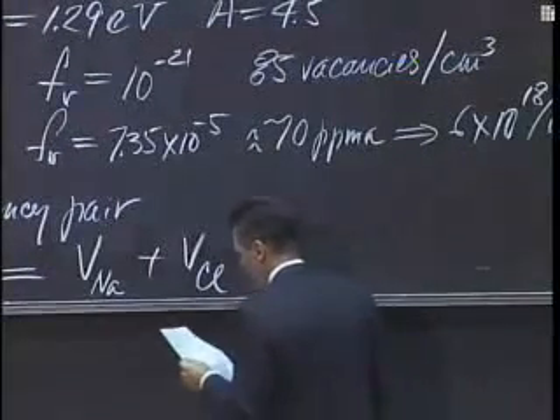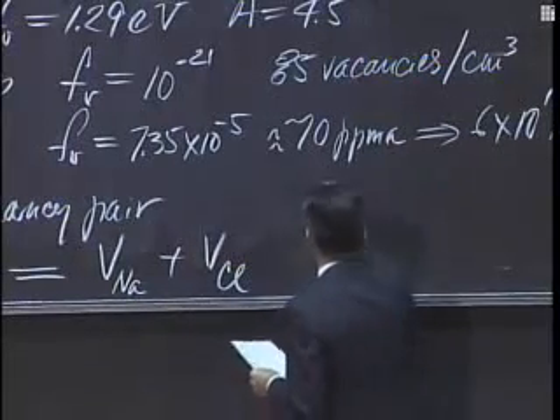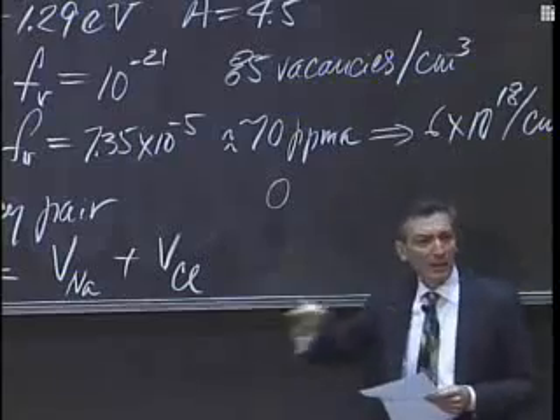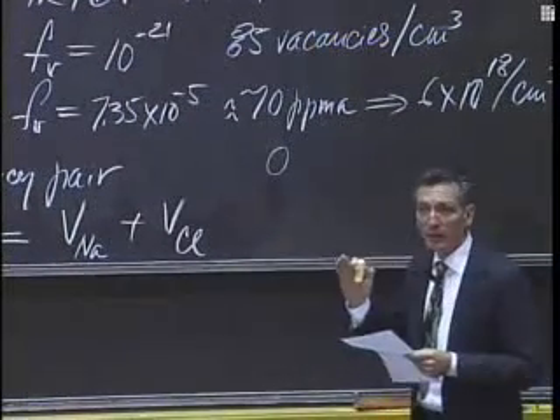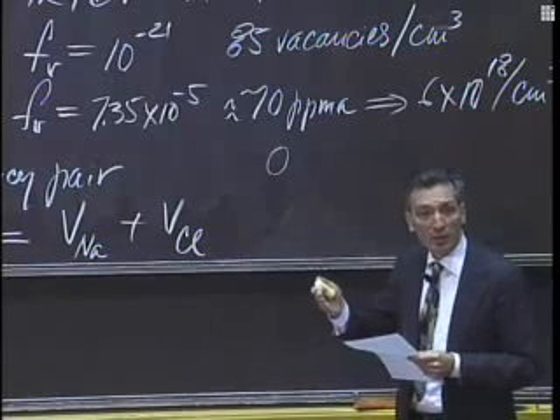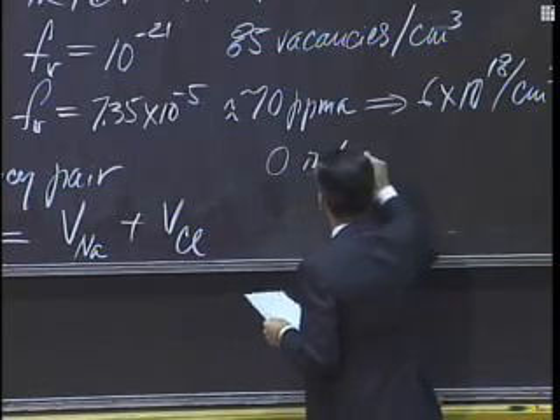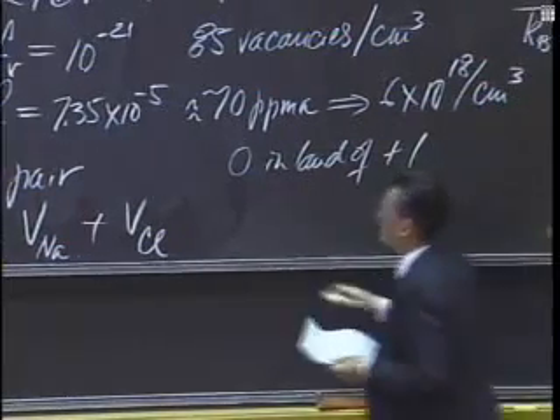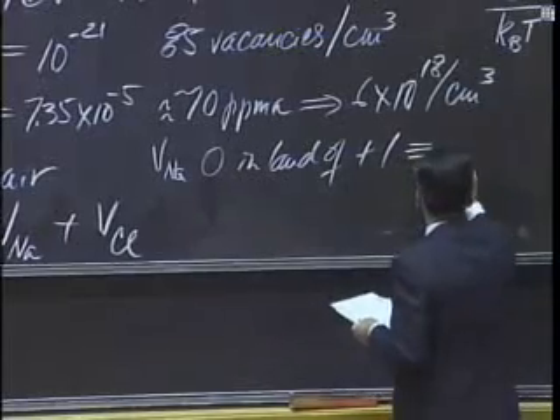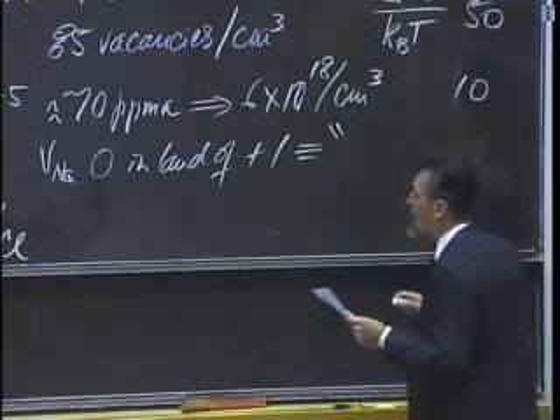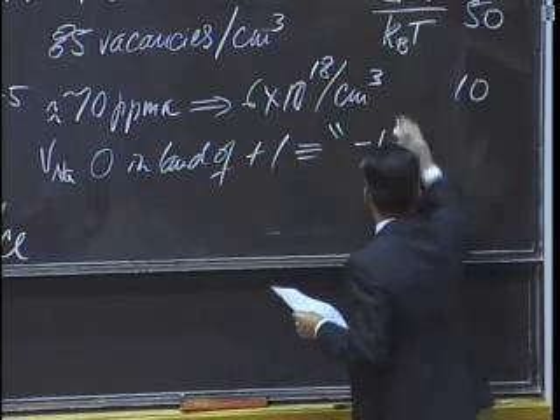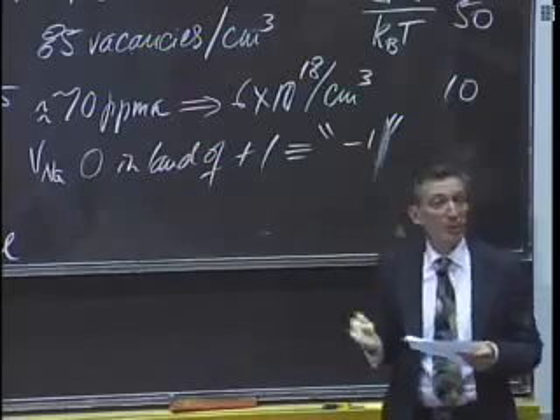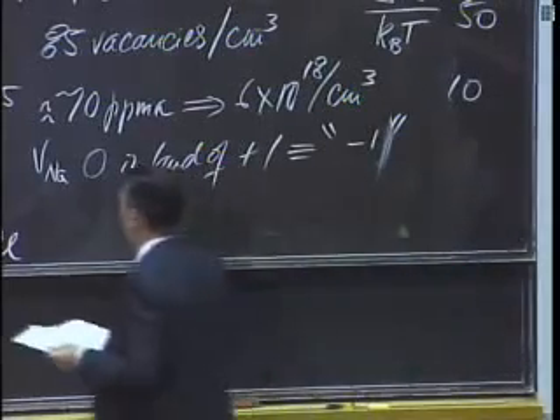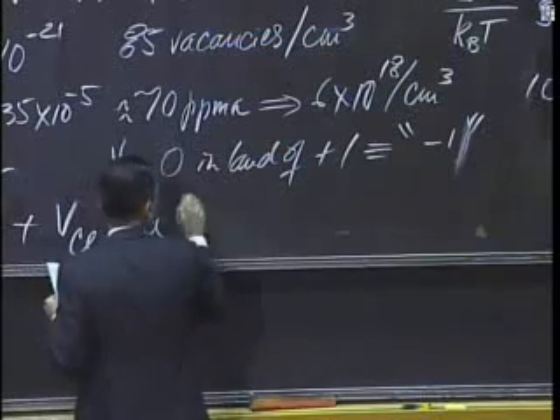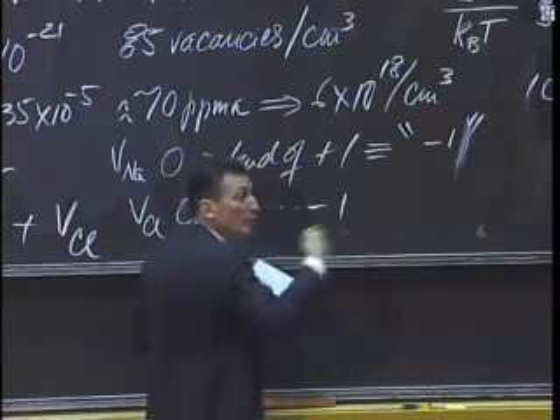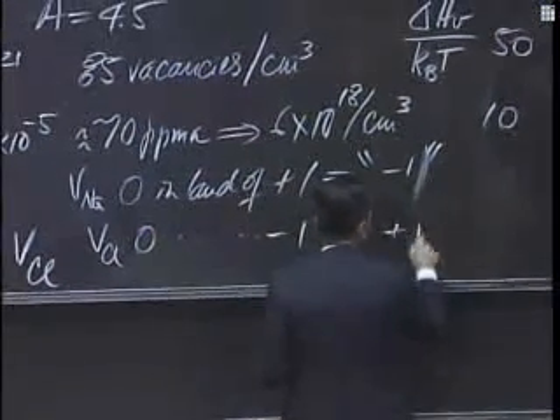Well, let's think about it. A sodium vacancy is charge 0, but it's on a cationic sublattice. It's 0, but everywhere around it, it's got neighbors of comparable charge, except this is in a land of +1 for V sodium. So this means it has an apparent, I'm going to put quotation marks here, apparent charge of -1. 0 in a land of +1 is relatively negative. And what about the chloride? The chloride vacancy is 0 in a land of -1. So a 0 in a land of -1 is effectively a +1.